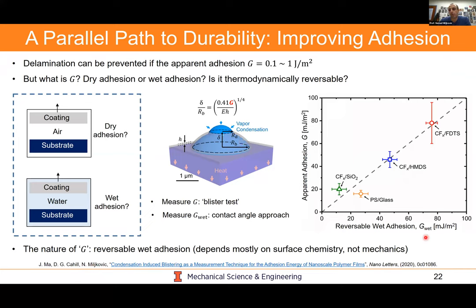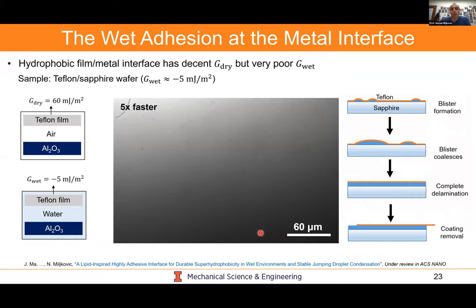These are some experimental measurements looking at the apparent adhesion versus the reversible wet adhesion, and indeed we get a fairly linear relationship, telling us we're on the right track. What you're seeing here is condensation on a surface that's been promoted with Teflon. Again, I hope it plays here. This video may not play, but essentially the coating has a good dry adhesion, but it could actually have a negative wet adhesion.